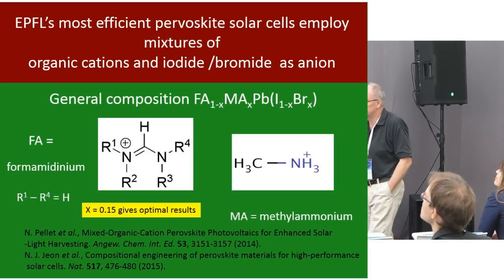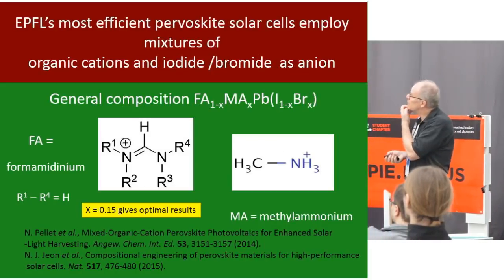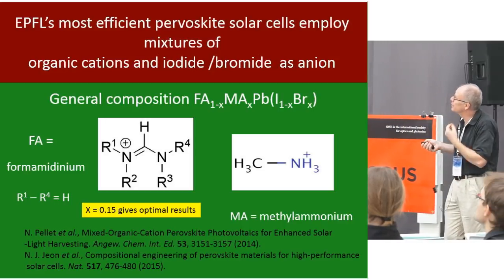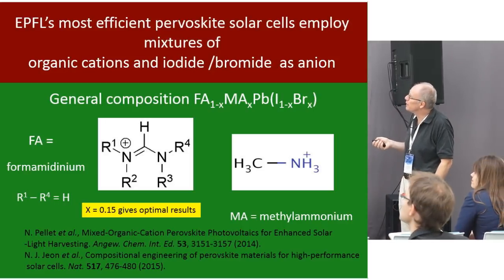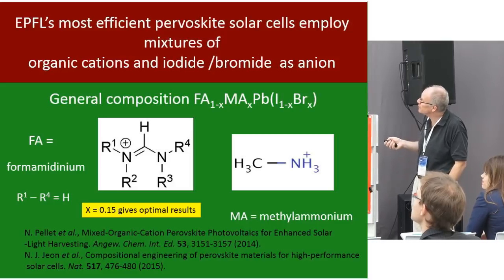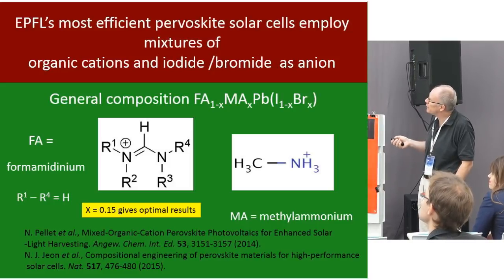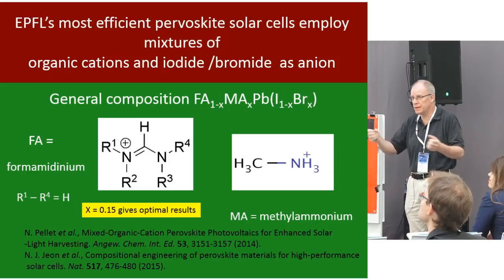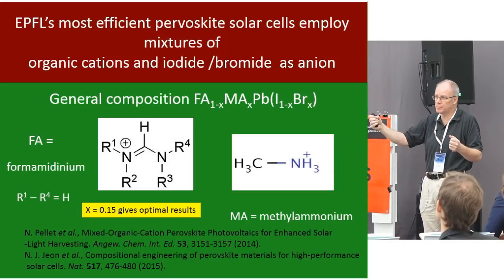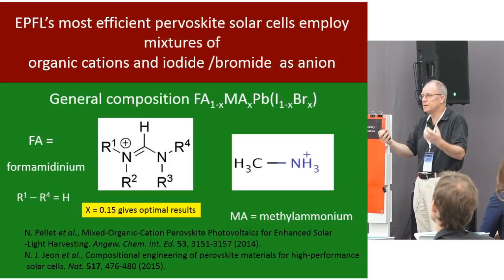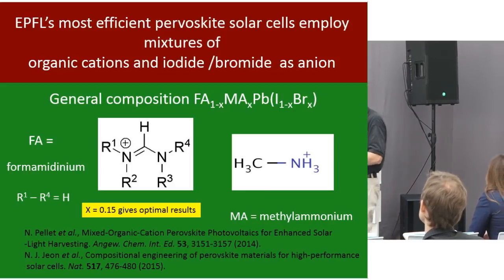Coming to what we do a bit at EPFL, we started to look into the chemistry of the perovskite, and you can basically manipulate the composition. Lead is there, then you have the iodide halide. You can mix in bromide as another halide. That tunes the band gap, so you increase the band gap with bromide, but also make the quality of the perovskite a little bit better.